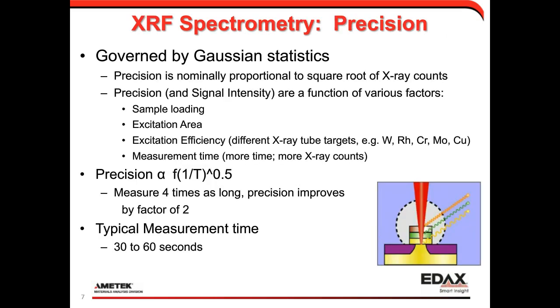The precision of XRF measurements is governed by Gaussian statistics. Basically what that means is the more time that we measure for, the more X-ray counts that we collect, and the more counts that we have, the better the precision in our measurement. Our precision runs to the square root of the number of signal counts that we have.